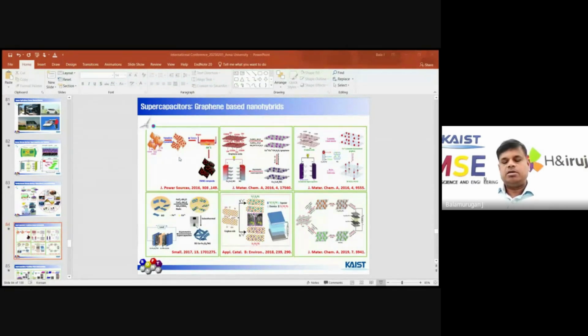When we use this kind of material, we have to use current collectors, and usually we use nickel foam. Why do we choose nickel foam? First of all, nickel foam is a highly porous network, which easily helps to adapt our materials and load more material, and the electrolyte easily penetrates into the active material to get higher storage performance. Therefore we use nickel foam. First we made the hybrid material with graphene networks, and first only a single positive or negative material. After we saw some problems with the negative material, like the durability issue of activated carbon, we fabricated both positive and negative materials to make full devices.